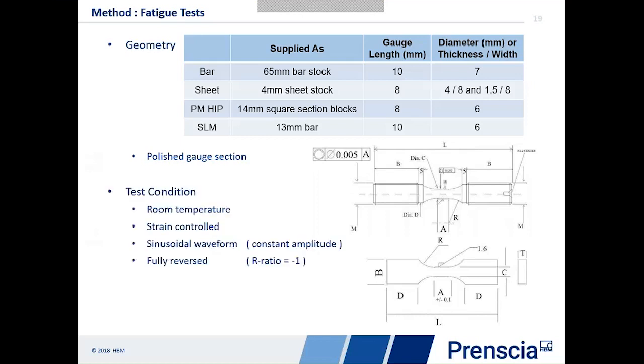And we can see here the gauge section and the specification that we've got for those fatigue specimens. All the tests have been done at room temperature. They've all been done under strain control using a sinusoidal waveform, and they're fully reversed tests, so equal compression and tension. And our failure criterion has been to look for a 20% load drop.